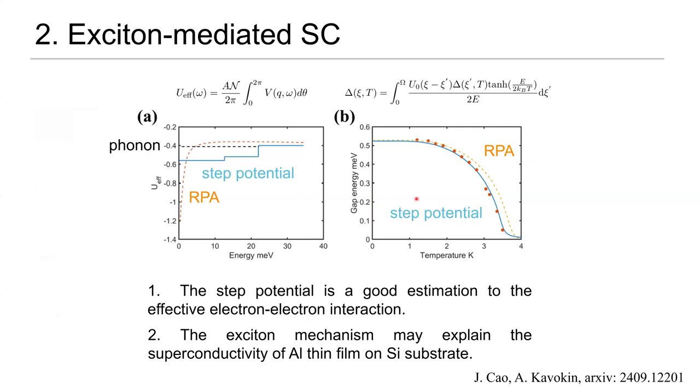And what about the pure aluminum? Pure aluminum, it will be a pure aluminum film without the semiconductor. 1.2 Kelvin. For pure aluminum metal, it will be about 1.2, where there's only phonon contribution. But this is for the aluminum thin film. So the critical temperature is about 3.5 Kelvin.